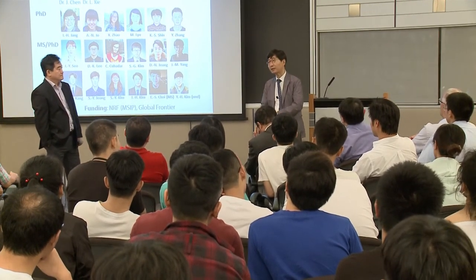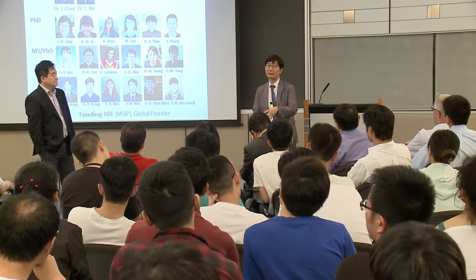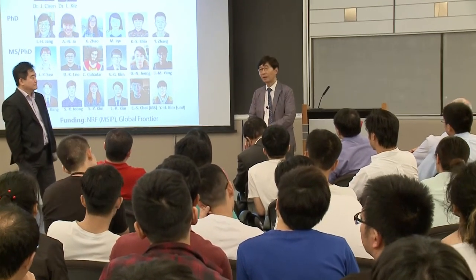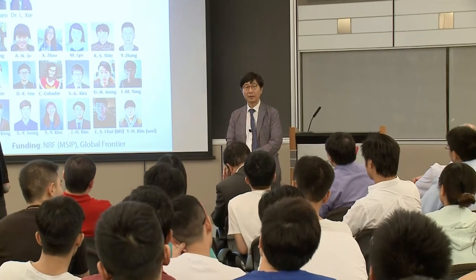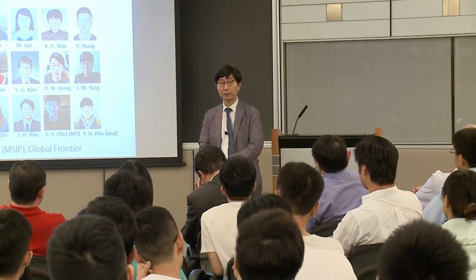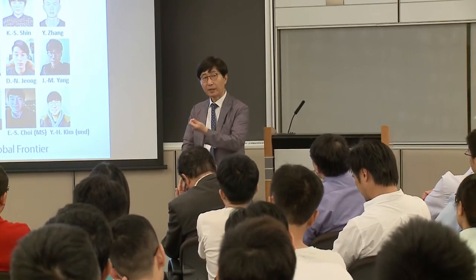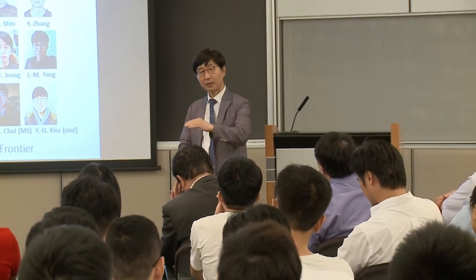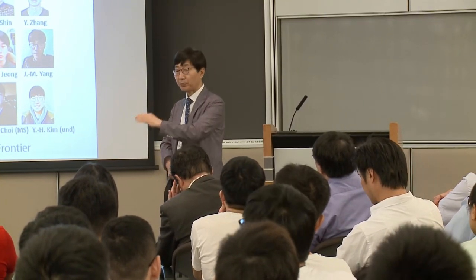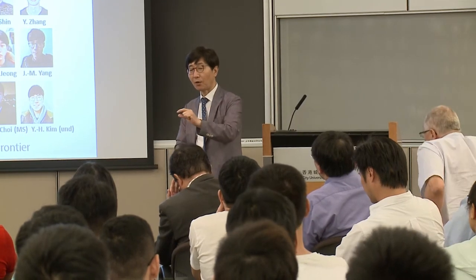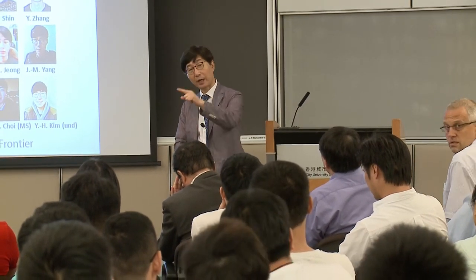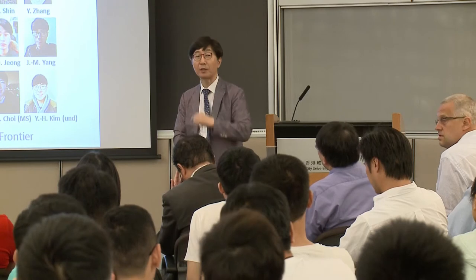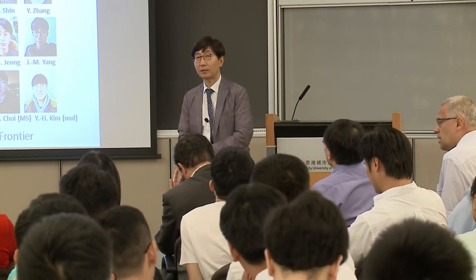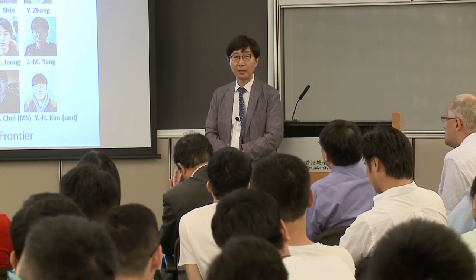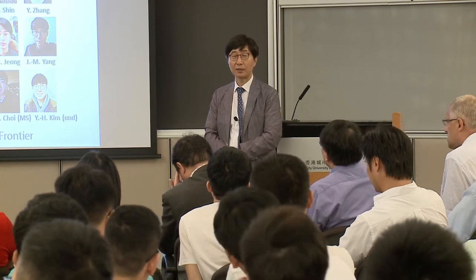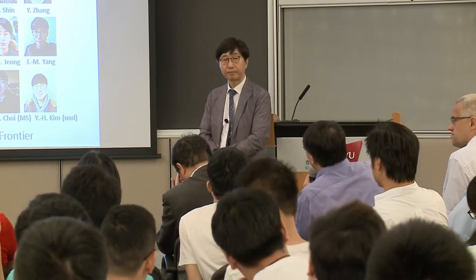So the material itself has very good defect tolerant properties, even if you do not manage it that carefully. But at the interface, for instance titanium oxide, tin oxide, PEDOT:PSS, the perovskite structure is probably different from the bulk property. So I think this is extremely important. This is my opinion.